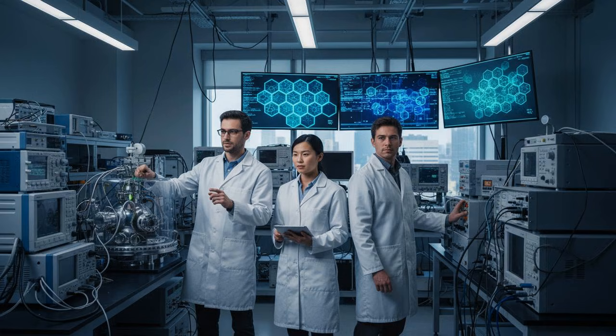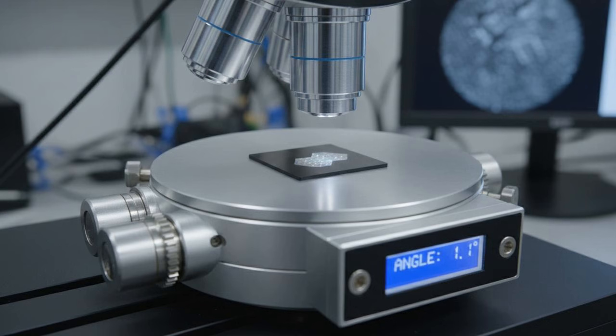They didn't use a $1 million nanofabrication machine. They used a technique called tear and stack. This relies on a clever bit of manual dexterity. If you take two different flakes of graphene from two different crystals, you can never be sure how their atomic lattices are oriented. You don't know where 0 degrees is. So the MIT team didn't use two flakes. They used one. They started with a single pristine flake of graphene on a substrate.